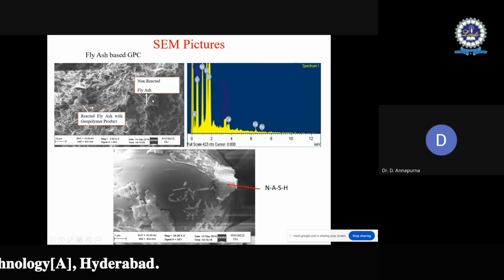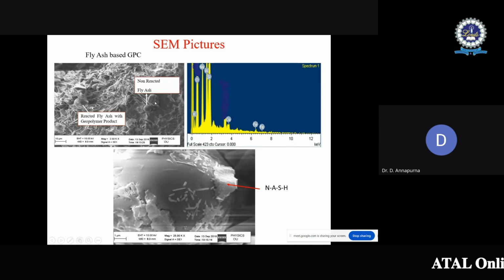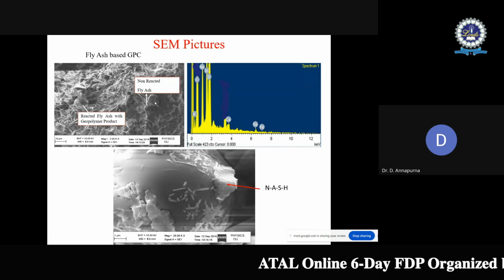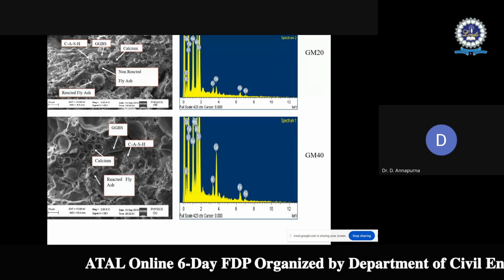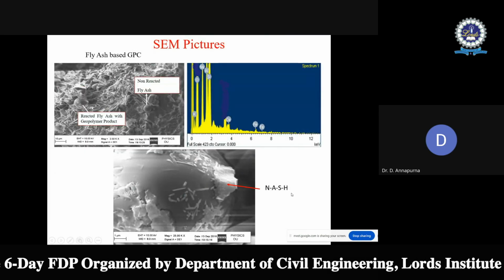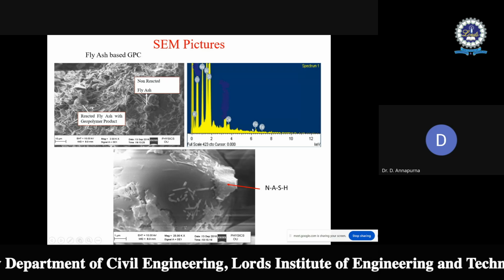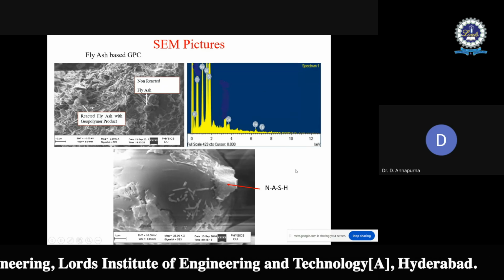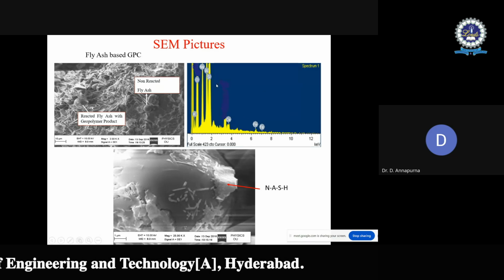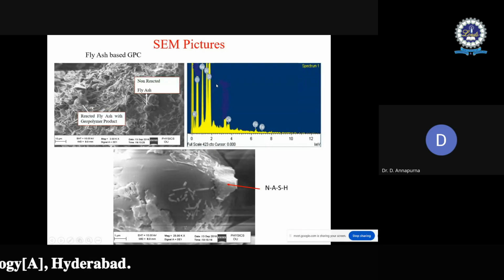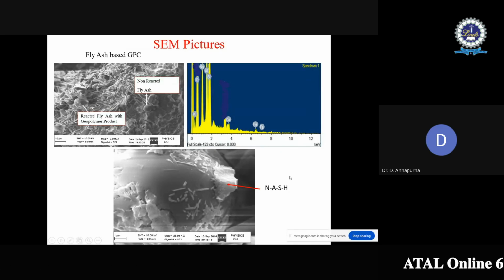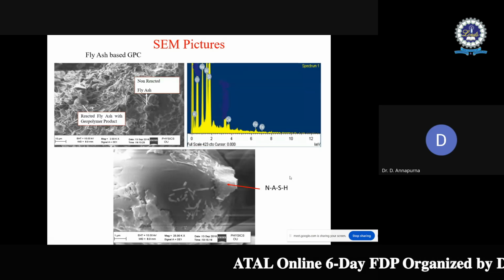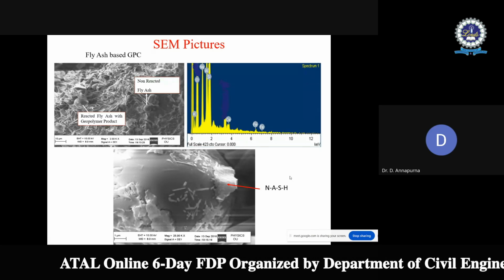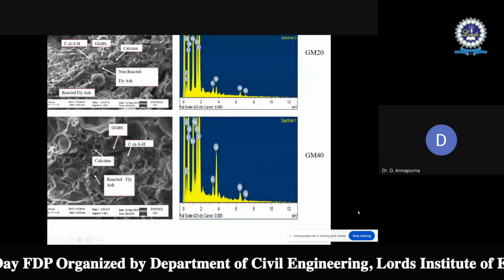In the 28 days fly ash based geopolymer concrete, more fly ash particles are seen without reaction products. And this is sodium aluminate silicate hydrate gel, which is confirmed through EDAX pics. Because in the EDAX pics, chemical composition percentage weights are taken into consideration, where the silica by alumina ratio is considered, which is coming between 1.5 to 2, confirming the presence of NASH gel.